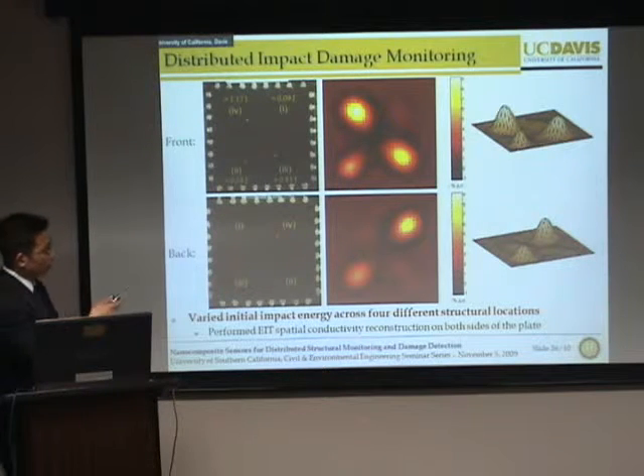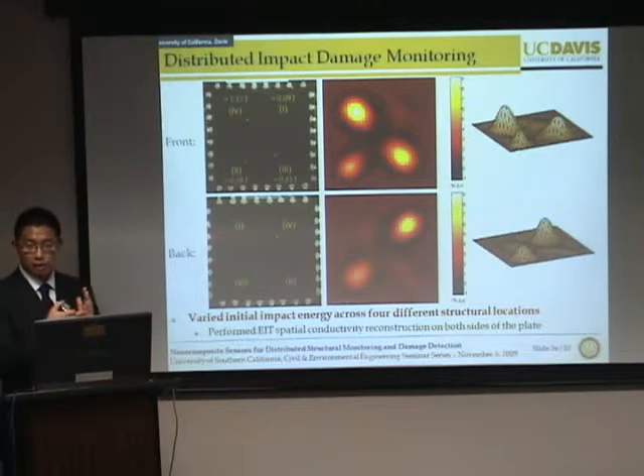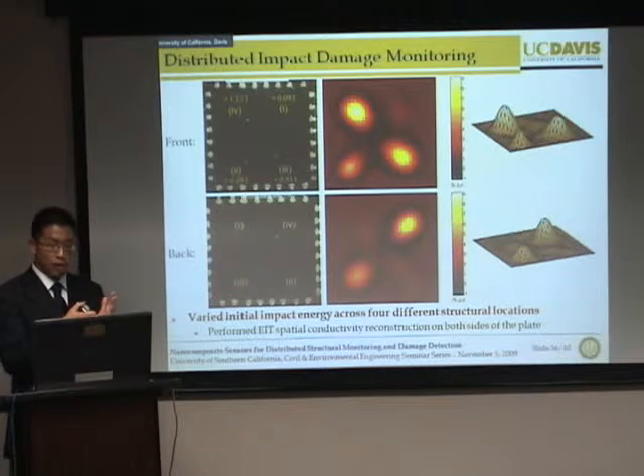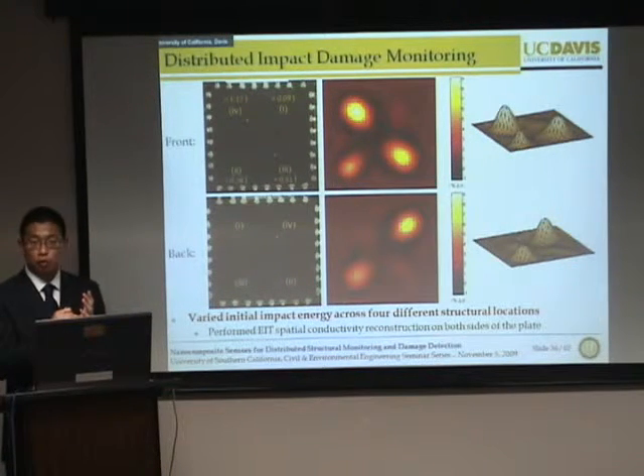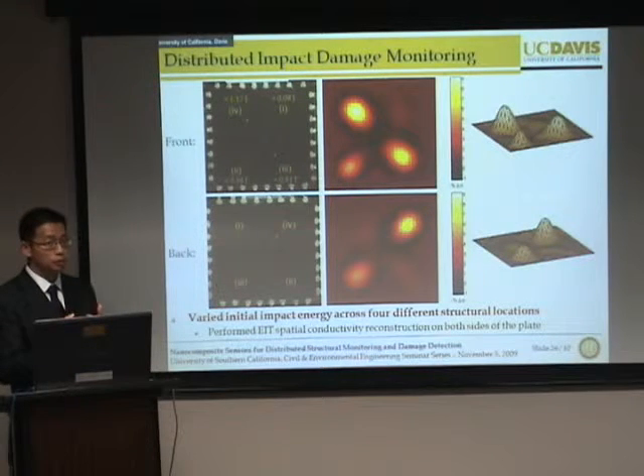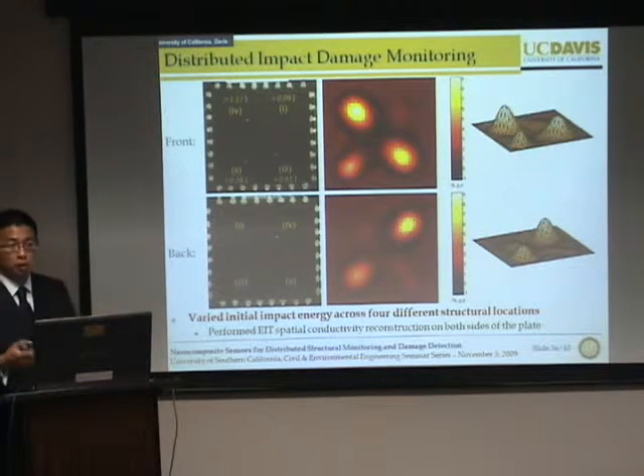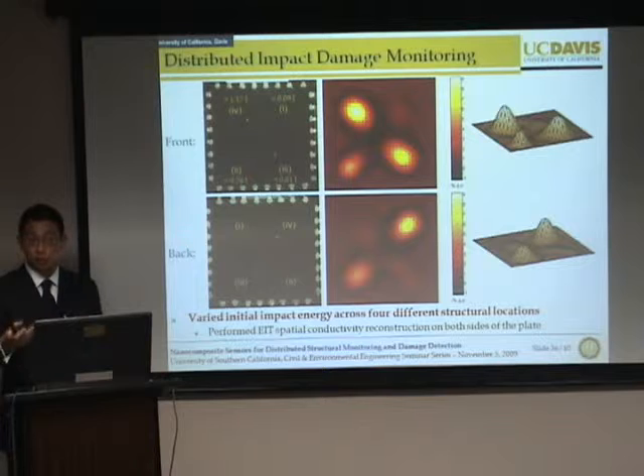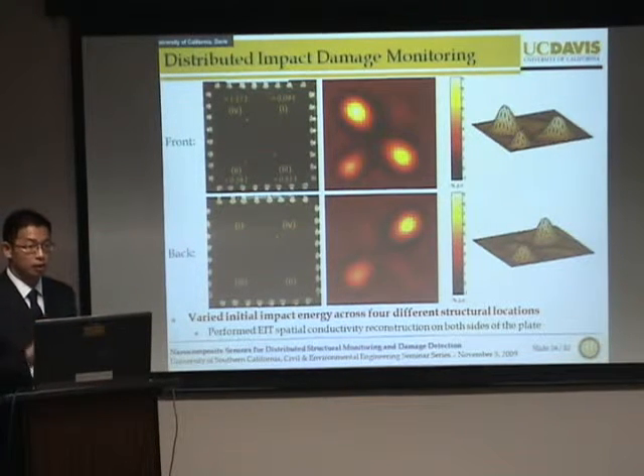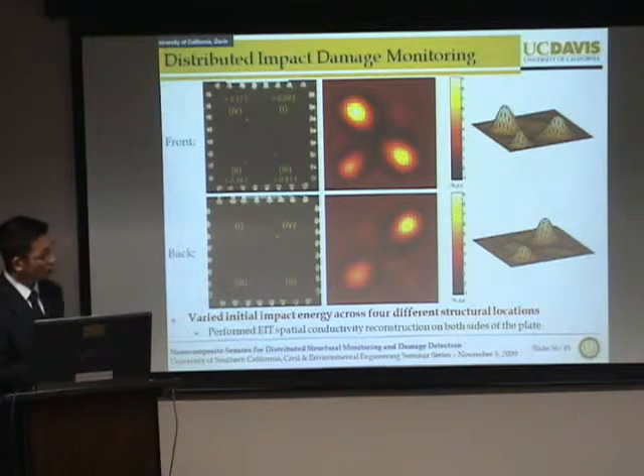So for some of these cases where we have high impact energies, the impact hammer actually etches off a little bit of the film, thereby imparting greater conductivity change. So some of these peaks correspond to the film being damaged in addition to the structure being damaged. But yes, you're right. So are these locations of the impact or the damage? These are locations of the impact. Both front and back? Right, both front and back.